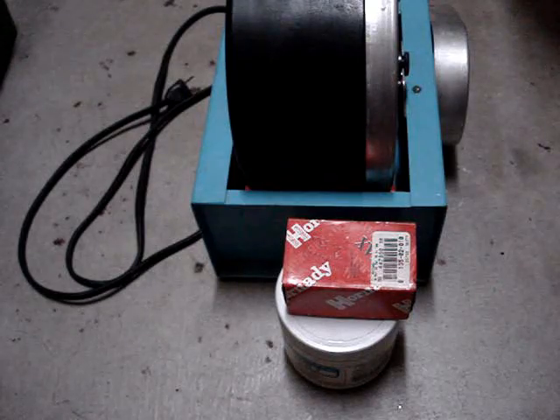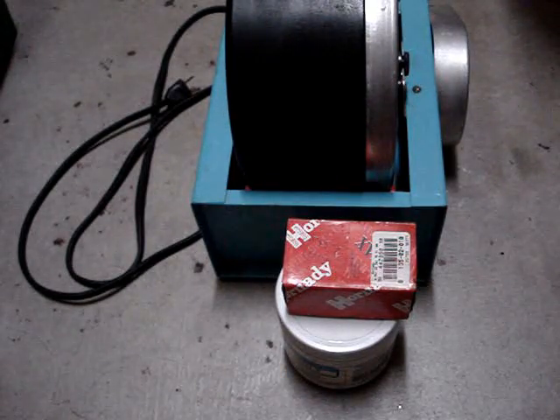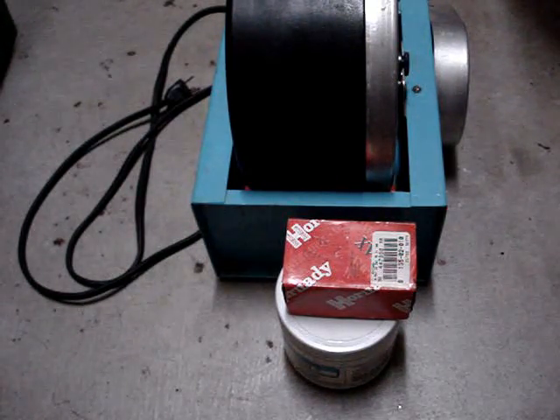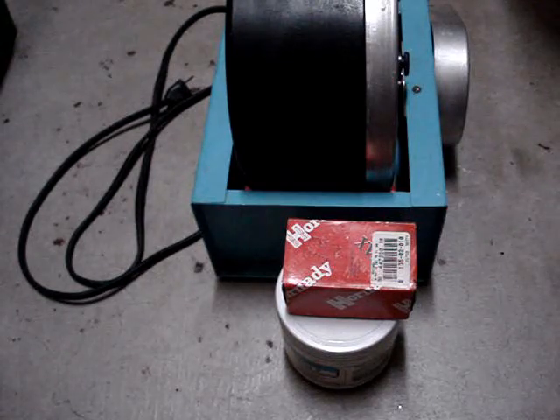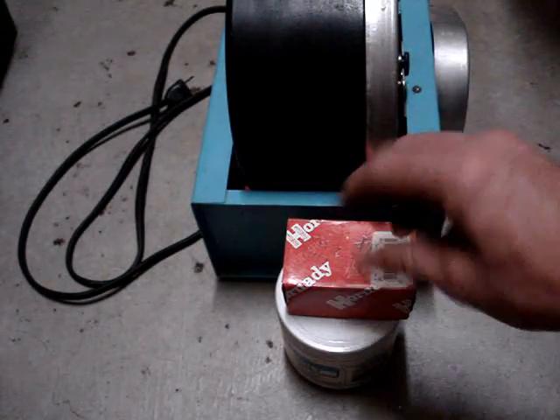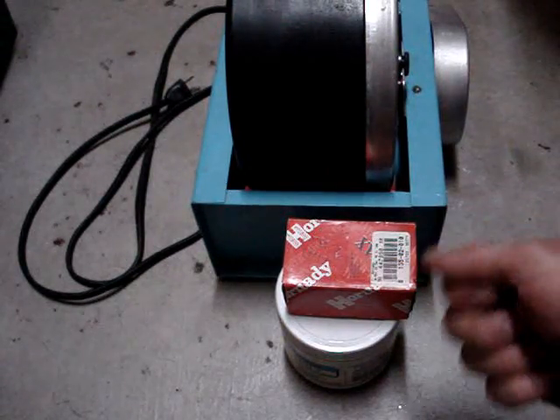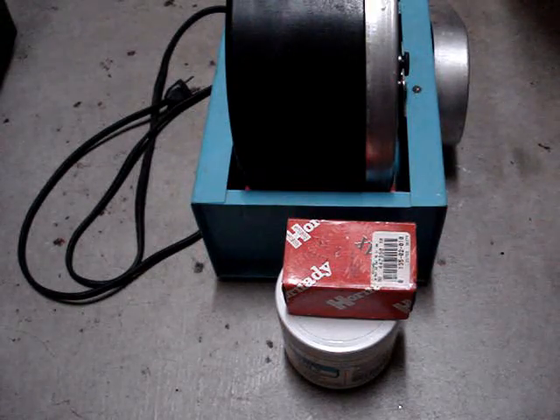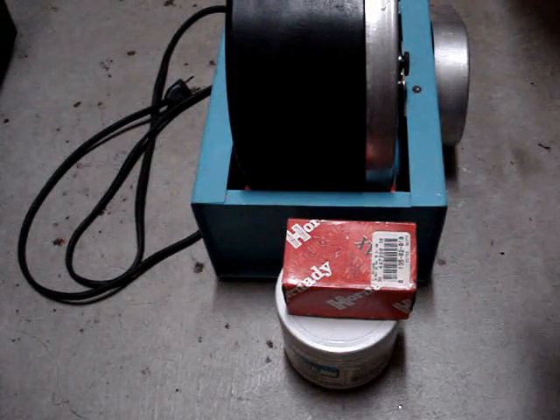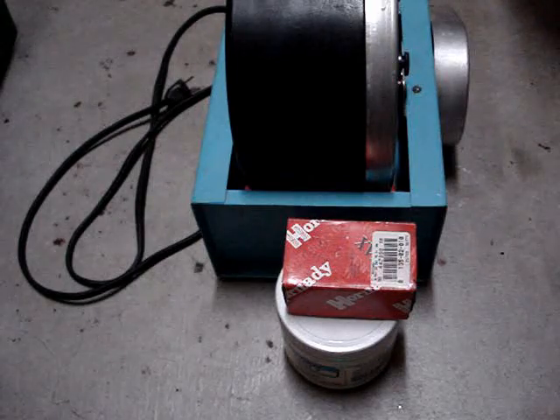What I use is I go to the drugstore and get 99% rubbing alcohol, and I put them in the little basket, submerge it, give it a gentle shake for like 30 seconds or so, pull it out, put it in front of a fan, and let them air dry.